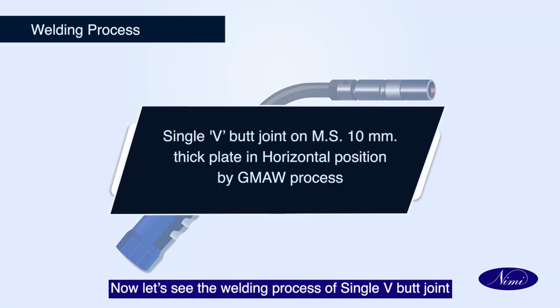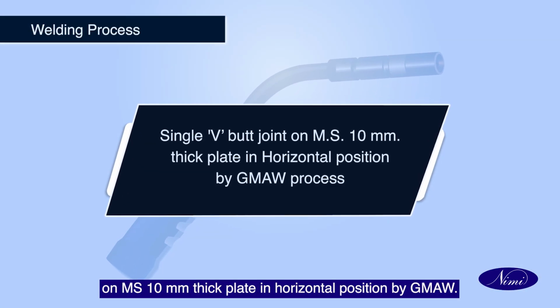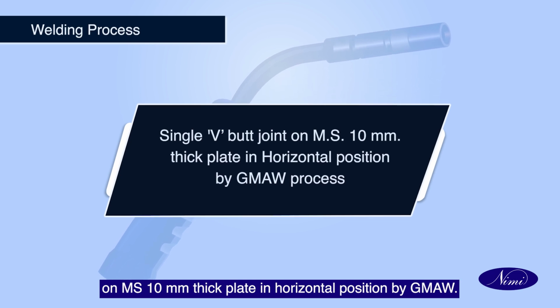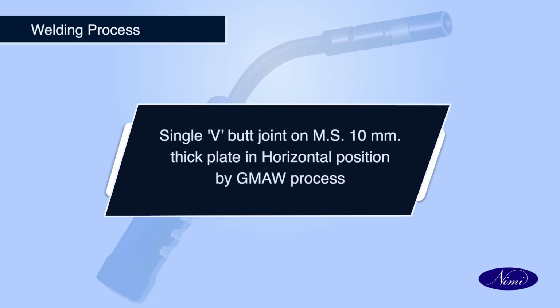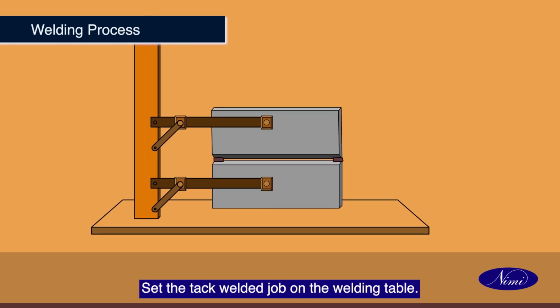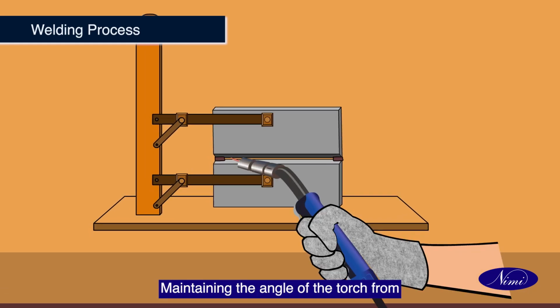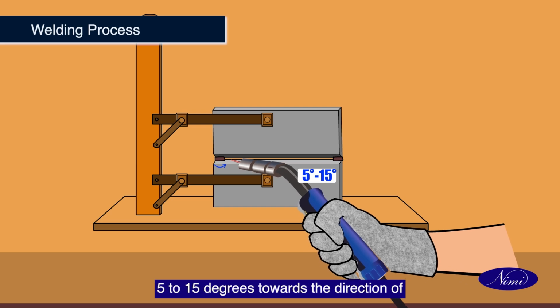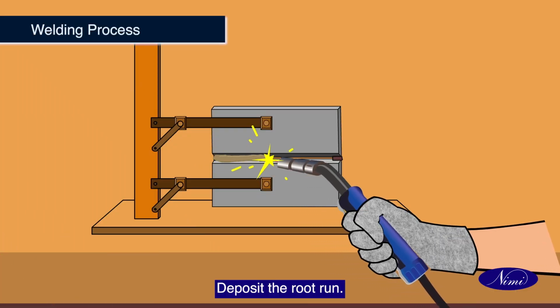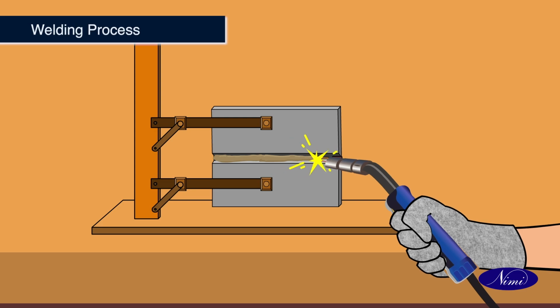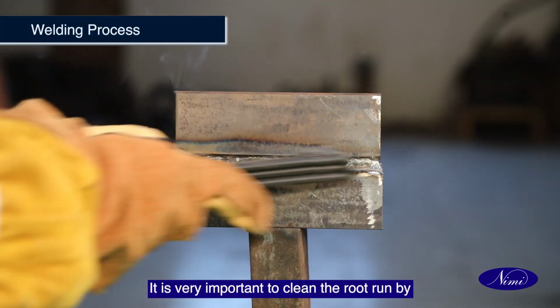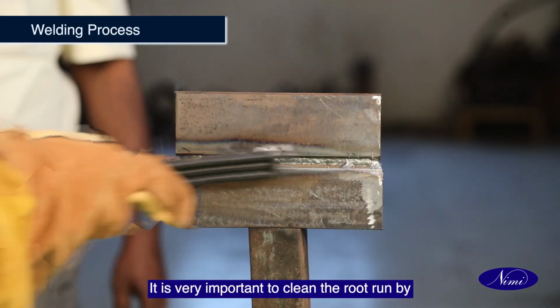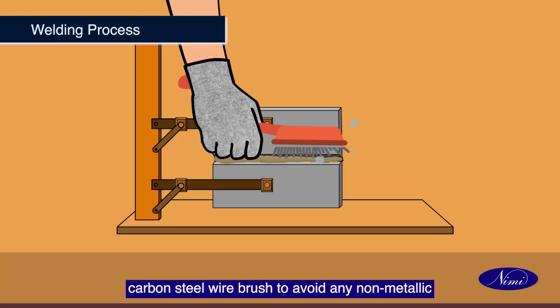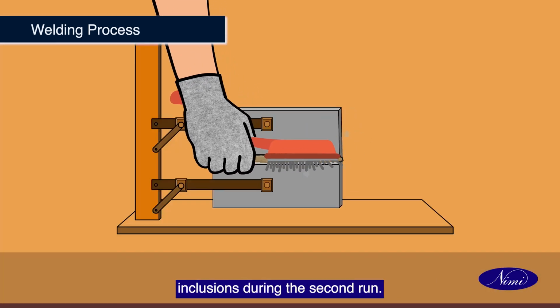Now let's see the welding process of single V-butt joint on MS 10 mm thick plate in horizontal position by GMAW. Set the tack welded job on the welding table, maintaining the angle of the torch from 5 to 15 degrees towards the direction of travel to get better root penetration. Deposit the root run. It is very important to clean the root run by carbon steel wire brush to avoid any non-metallic inclusions during the second run.